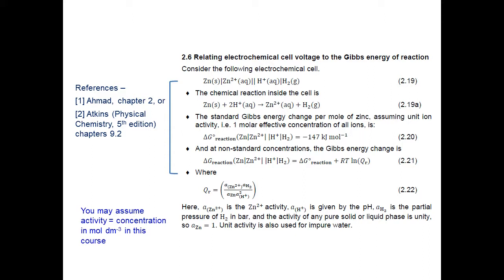And the process we're going to be worrying about is, does a cell reaction take place with our metal of interest at the anode? So consider the electrochemical cell that we're talking about, the zinc dissolution cell in acid, equation 2.19. We take as a starting point in this course that we can do physical chemistry. If I wanted to know in physical chemistry terms whether this process happens, and I don't care about any other possible oxidizing agents, I would just look up the standard Gibbs energy change of reaction. That's equation 2.20, and this is a very big negative Gibbs energy change, minus 147 kilojoules per mole of zinc. Therefore, I expect that this zinc dissolving in acid really definitely does happen. And that's all I would need to do.